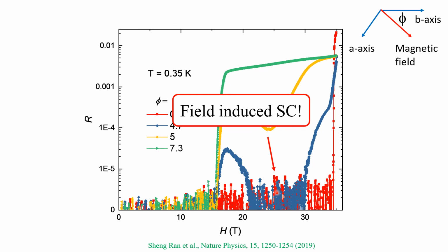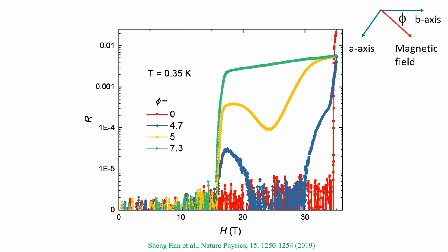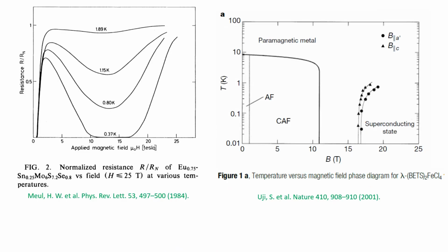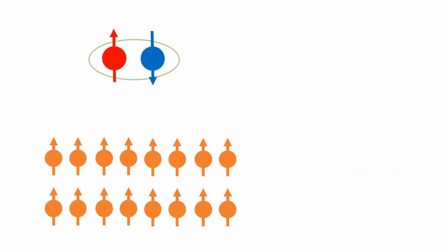Now, in this field range, magnetic field actually helped to stabilize the superconductivity. This is called field-induced superconductivity. Now, this is a very surprising result, but it has been seen. Here I'm showing an inorganic compound and an organic compound. In both cases, in some magnetic field range, it induces superconductivity. Now, this can be understood in terms of the Jaccarino-Peter effect.